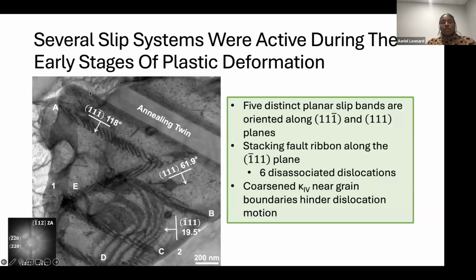One of the first things we noticed is that we had several different slip systems that were active during just the early stages of loading. You can see here that there are 5 distinct planar slip bands oriented along the 111 planes. You can also see here that we have a stacking fault ribbon that is connecting 6 dissociated dislocations.